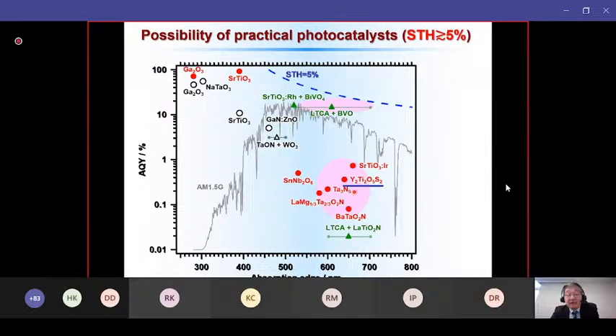Now let me just use this oxysulfide material as an example. If we like to achieve the STH value of 5%, we need to achieve about 30% apparent quantum yield. If we like to achieve 10%, we need beyond 50% AQY. And is it really possible to achieve these numbers?